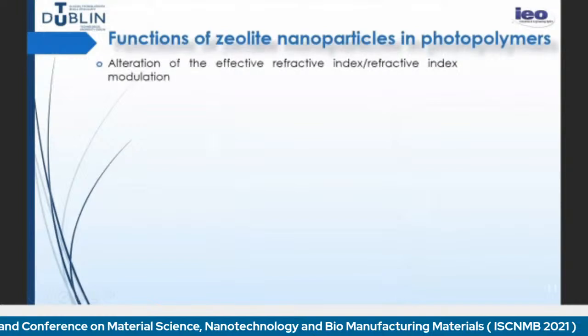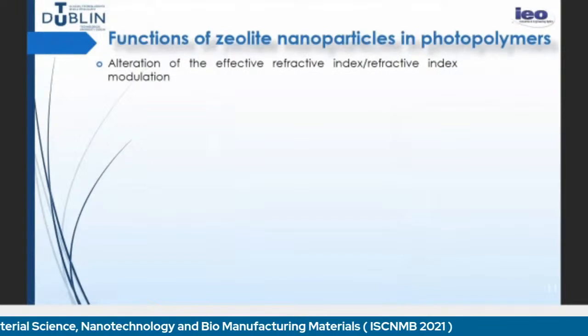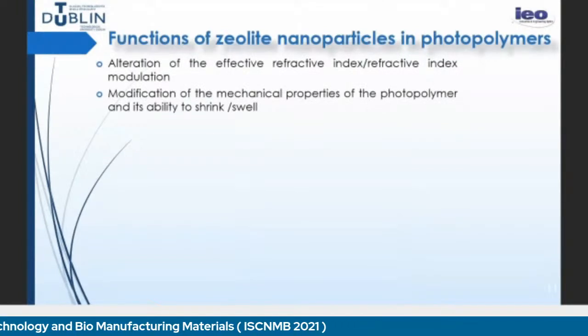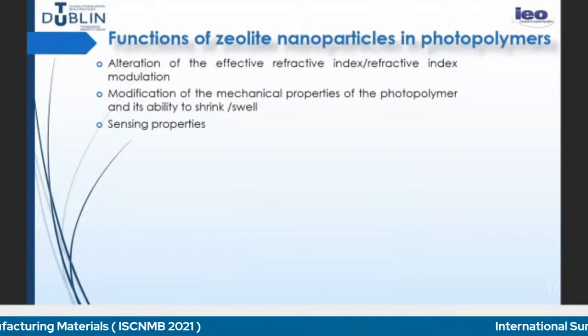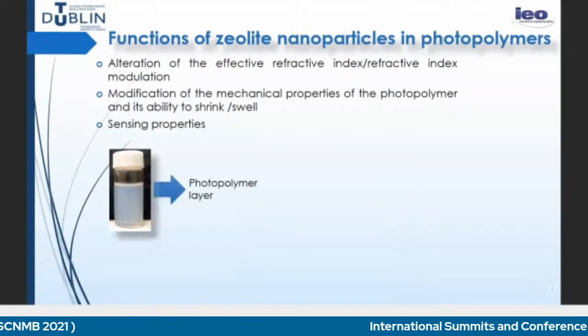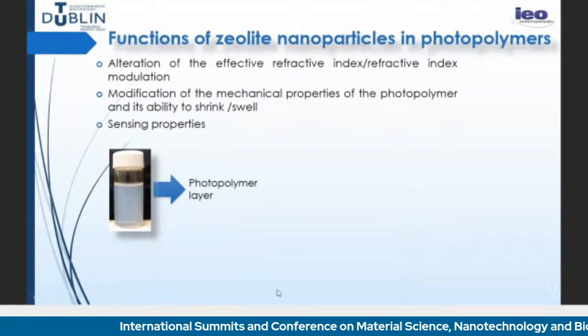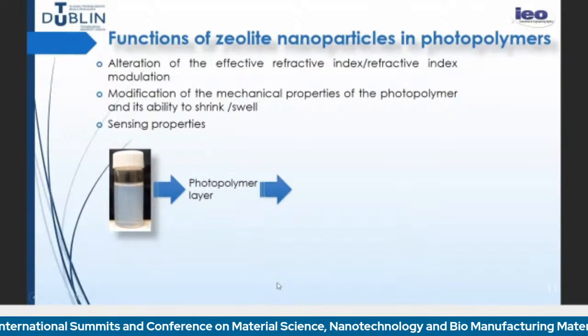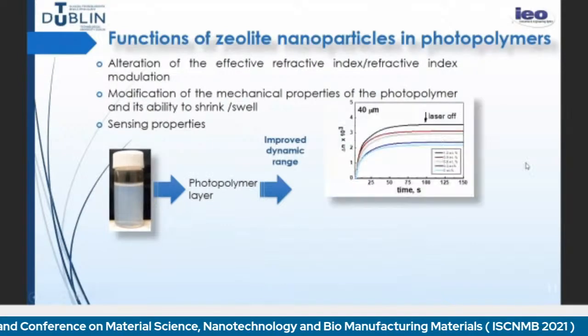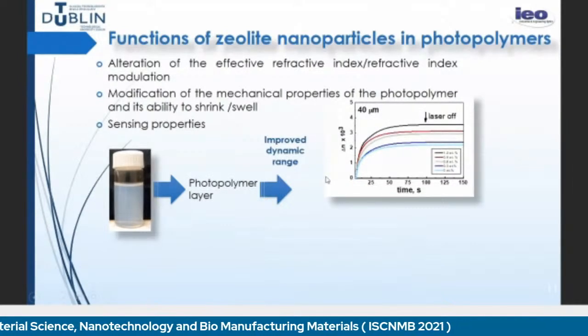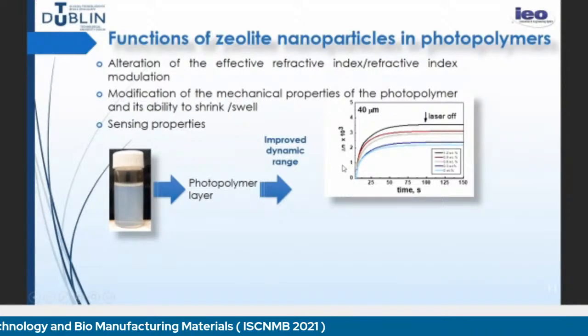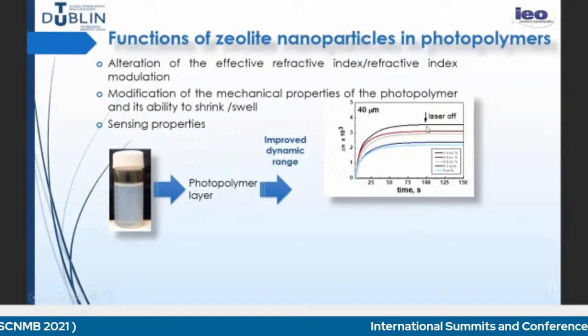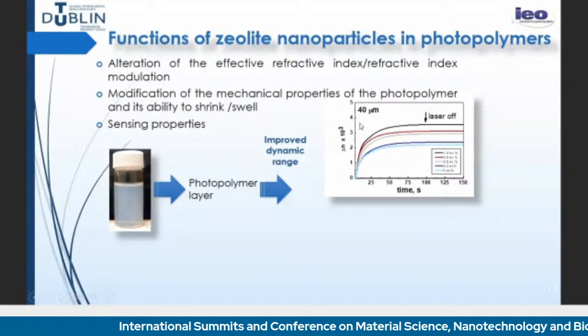What is the function of the nanoparticles? They change the refractive index, as I said. They modify the mechanical properties, the shrinkage, and they introduce sensing properties. So this is a 10% concentration of zeolite solution, a very high percentage. And this is just an example of how they improve the dynamic range. This is the change in the refractive index modulation with time for different concentrations, and you can see how the refractive index modulation is improved by adding nanoparticles.